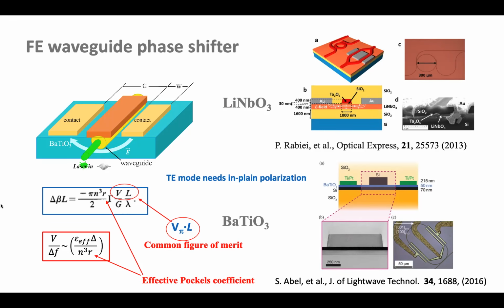The figure of merit for such a device is the so-called V pi L. It says how much voltage for a given length you need to apply to change the phase by pi. If you make two paths like this and shift one by pi, you'll get no light at all. And so now you have a modulator. You can go like Morse: 0, 1, 0, 1. Materials like lithium niobate and barium titanate have been tried and they work. This, for example, is a racetrack modulator, and this is called a Mach-Zehnder.